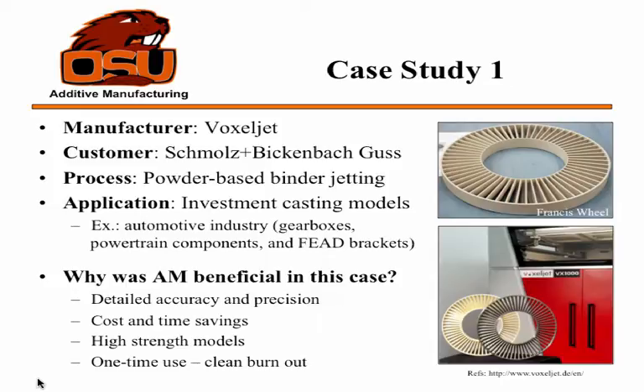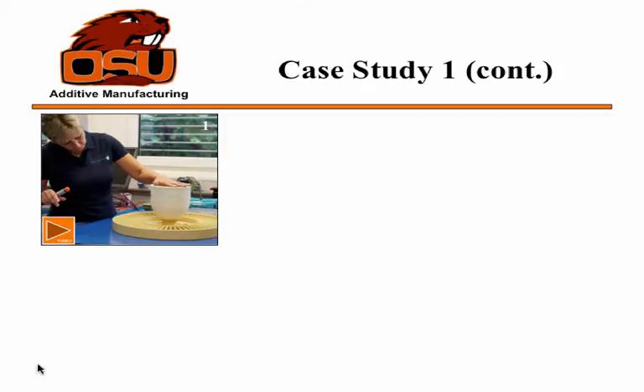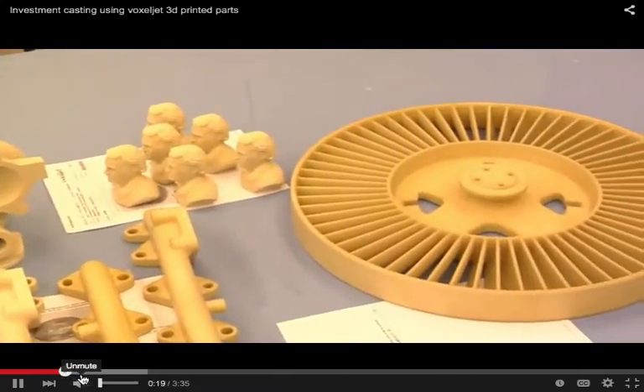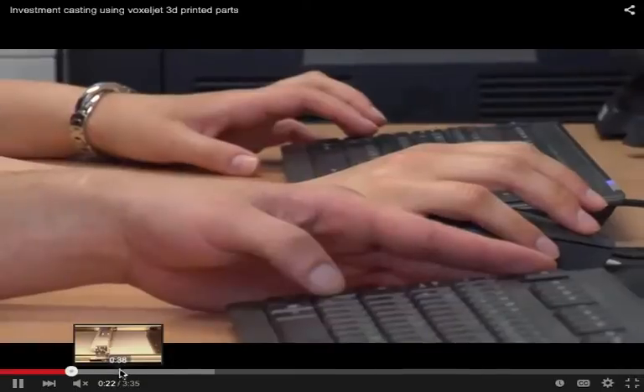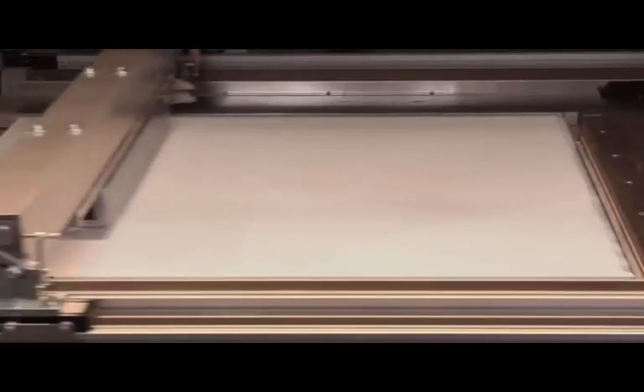What they do with these models is they'll make them and dip them in wax, and then they'll put them in the kiln and burn out that mold, and actually, because the PMMA shrinks, it doesn't break that ceramic coating. So the mold is really, really good, as we'll see in the video on the next slide. So here's the process, and this is a different type of part they've made. I'm going to skip ahead to the actual printing process. So here, there's the binder jetting process. They're building up that investment lost mold for that Francis wheel.